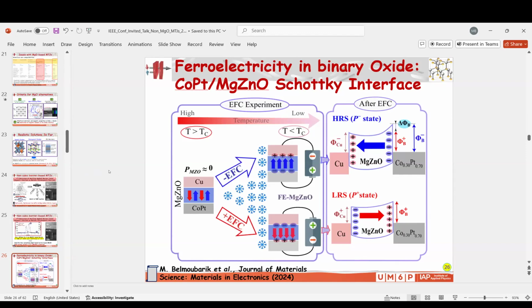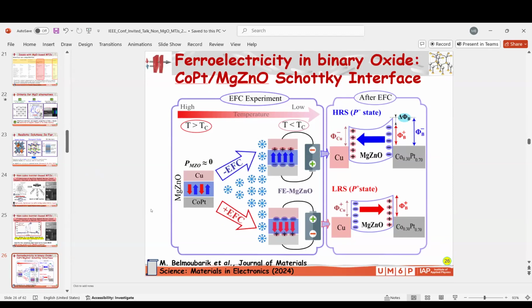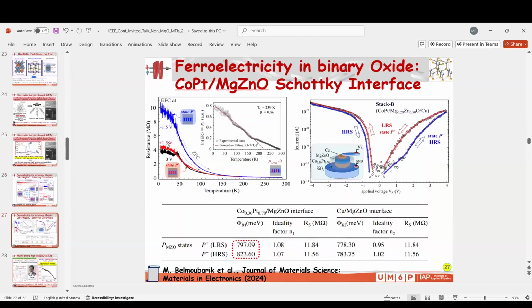We took the electric field cooling and magnetic field cooling used when measuring the exchange bias at the FM/AFM interfaces, and we applied it to our barrier. Here we use electric field cooling to clarify whether or not you have a ferroelectric. We realize this with plus/minus voltage, and we see a big difference by using some models that relate the tunnel electroresistance and the reversed electric polarization.